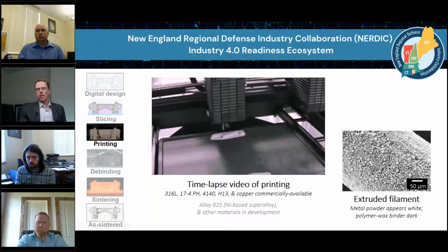If we look at that extruded filament through an SEM, this is the entire extruded filament. The diameter across is roughly 400 microns. The black regions represent the binder, and the white regions are the metal powder. Here we can see the metal powder is mostly spherical, and it's on the exterior. It's also all the way through; it's just that with the SEM, you don't see the interior of the extruded filament.